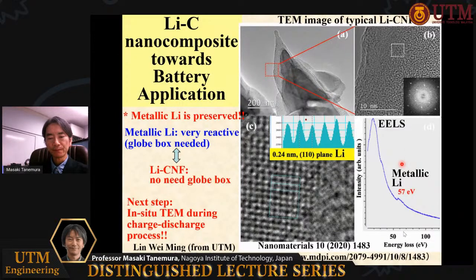So, in the lithium-dispersed carbon system, metallic lithium is preserved even after exposure to air. You know, lithium is very reactive to air, and usually we need a glove box to handle lithium. But for this lithium-carbon nanocomposite, a glove box is not needed. This lithium-carbon nanocomposite will be a very promising candidate for the next generation of lithium-ion batteries for easy